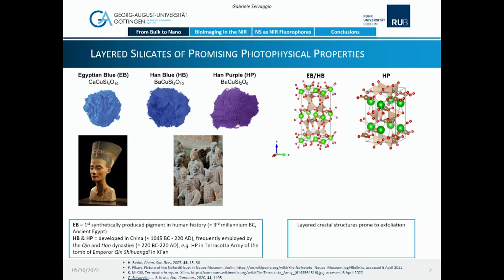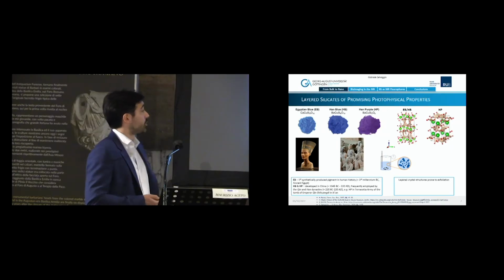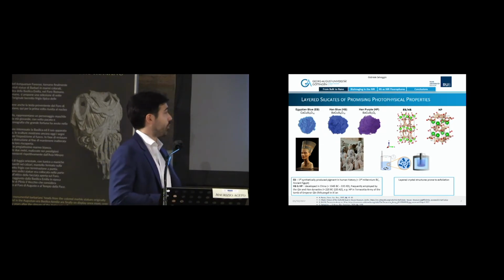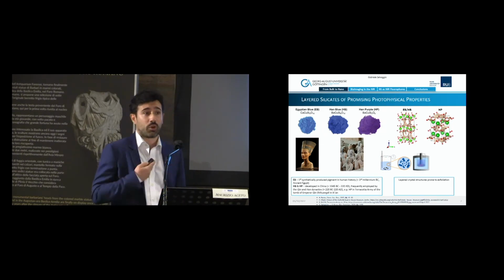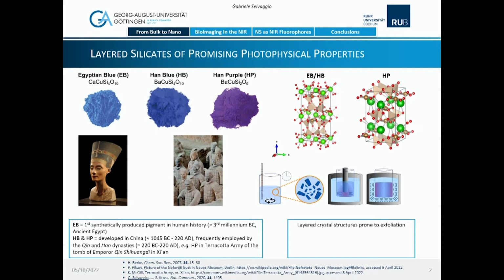The quite funny thing, in my opinion, is that it's extremely easy to exfoliate these materials. One can also do this by simply stirring these powders in hot water for 2 weeks, and you get already 2D exfoliated material. There are also other methods which employ, for example, tip sonication or bath sonication, or you could move towards the geology direction, so use, for example, wet ball milling.